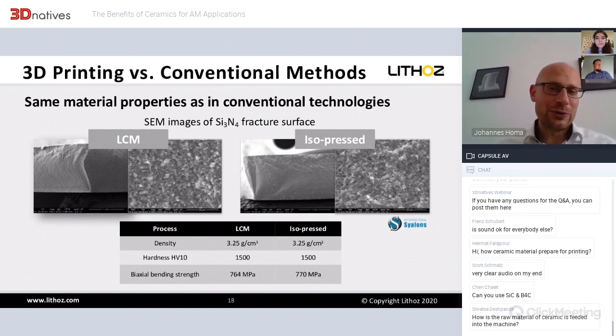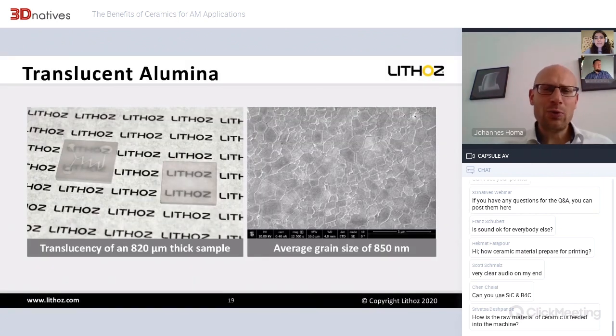And I also want to stress one other material, which is alumina. This is a polycrystalline material and not like glass where you can see through. But if you treat it very well, you can get it translucent, and as you can see here, you can read through that. And this is actually a proof that we can build without any problems.